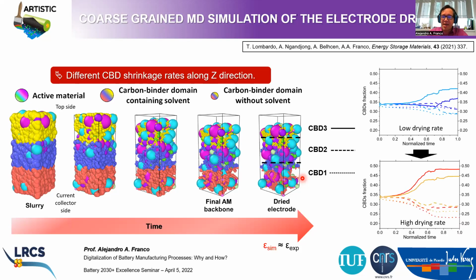And this is something that can also be very nicely quantified. I mean, if you track the evolution of the CBD volume fraction along the thickness of this slurry that is becoming an electrode, you see that for high drying rates, if you focus, for example, on this series of 3 red curves, there is a high heterogeneity. You have much more CBD on top than at the bottom, right?